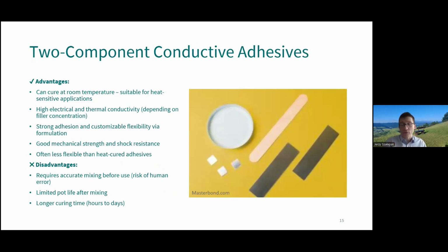Due to the temperature requirements and search for higher mechanical strengths, two-component adhesives are widely considered. We can find quite many options on the market, from MG Chemicals through Panacol, etc. Although not all of them are room temperature cured. The ones that actually are tend to have quite high shear strength resistance. But on the other side, the resistivity of these adhesives is higher than for one-component materials. And what's more, most of them are quite brittle. They do not perform well in bending tests. At least the ones I had the chance to test were breaking within the first few testing cycles.